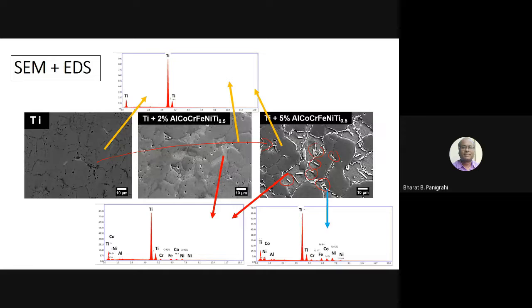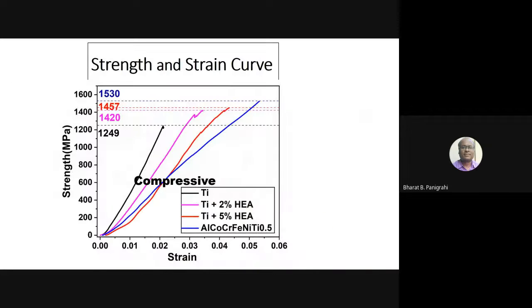Okay, we go for detailed analysis, not to worry about. If you look at compressive strength, you can see there is a gradual change in it. So this black line shows the strength. The compressive strength of pure titanium is close to 1200, but this can jump to almost 1500 MPa by using the high entropy phase. So there is a massive jump from 1200 to 1500 megapascal by using just a small quantity, 2 and 5%, of high entropy alloy.